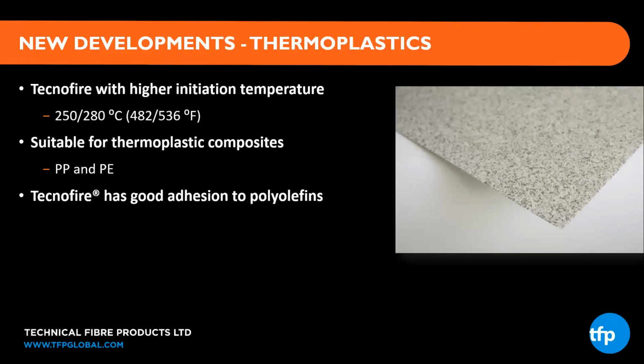We are always looking for new developments to satisfy growing market needs, and the current commercial grades activate at either 190 or 220 degrees centigrade as highlighted, but we are working on grades with 250 degrees C, 482 degrees Fahrenheit, and 280 degrees C, 536 degrees Fahrenheit activation temperatures to open up more thermoplastic applications, such as polypropylene and polyethylene, which Tecnofire bonds well to.